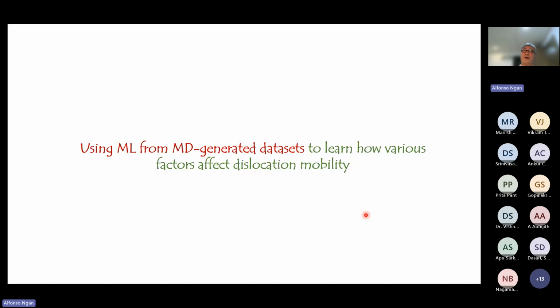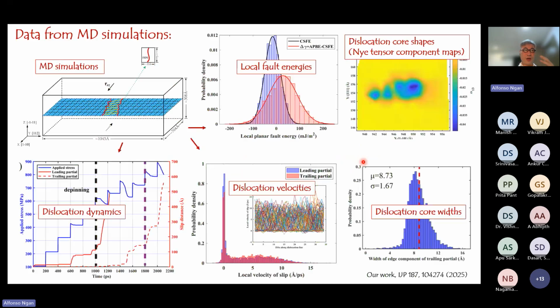So in the next part, we are going to use machine learning from molecular dynamics generated data to learn objectively which factors in the alloy contribute more to lowering the dislocation mobility. So this is typically how you run an MD simulation: you generate a block and then you pass a dislocation, apply some stress. The dislocation may be dissociated into two partials like this. And you can regenerate the cell and rerun this many times. So out of many attempts, you end up with a lot of data.